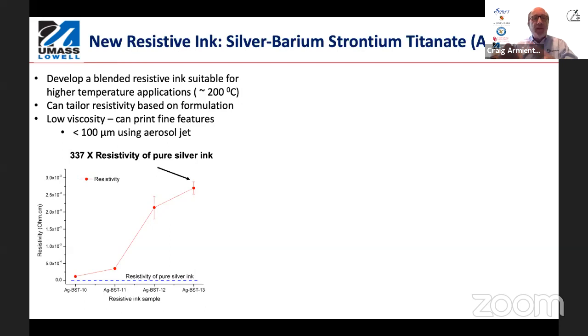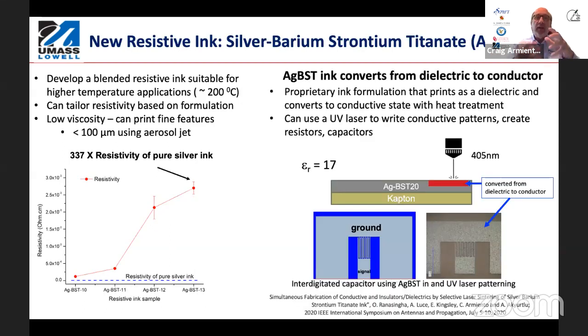But in the course of developing this resistive ink, we came up with a formulation now of a particular formula. Okay, thanks. It's AGBST, where we can actually print it as a dielectric with the dielectric constant of around 17, use a laser to selectively heat it and convert it to a conductive.